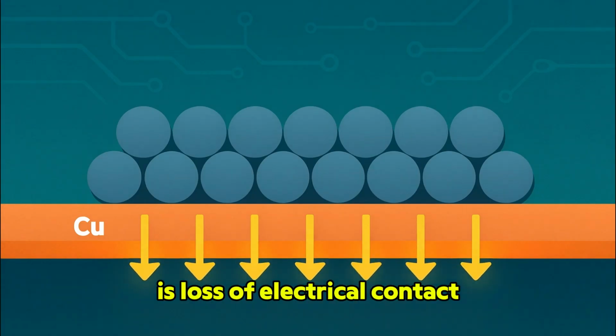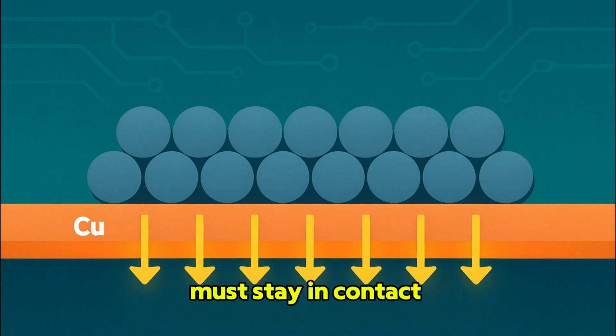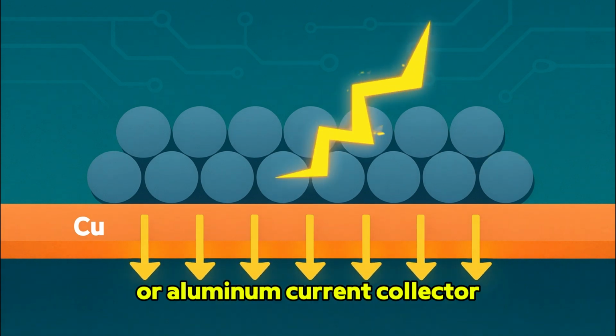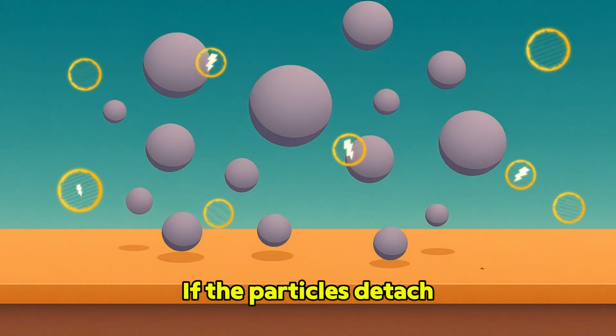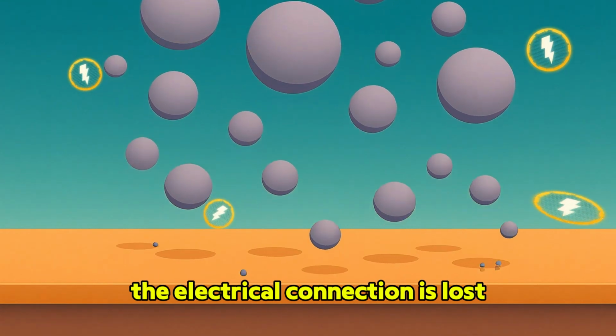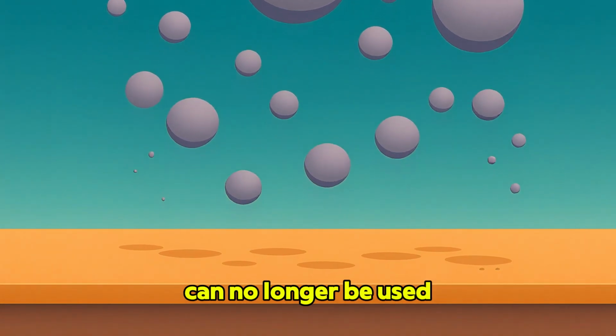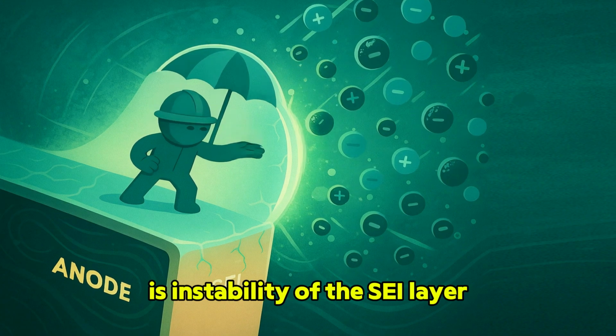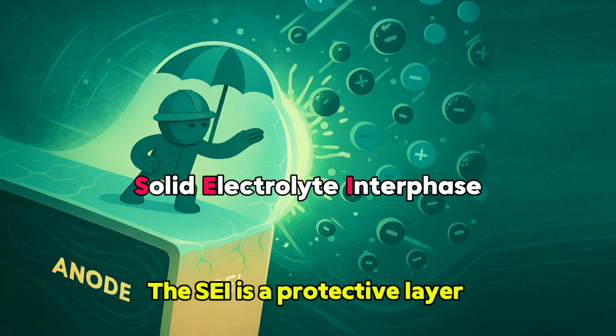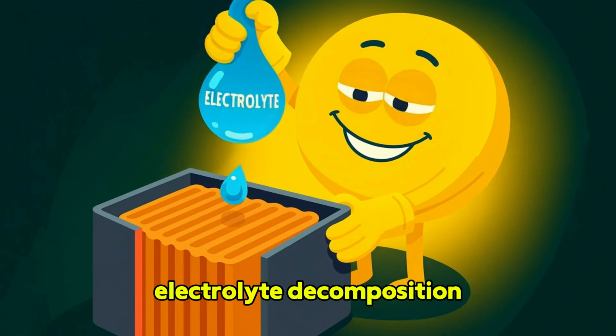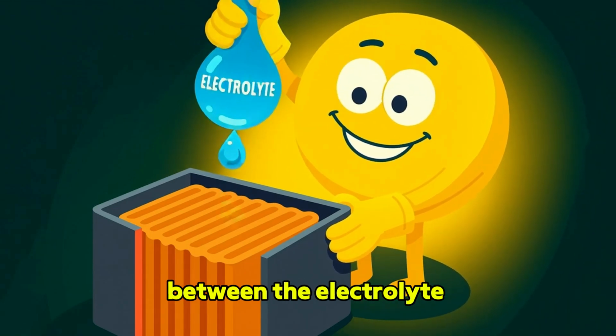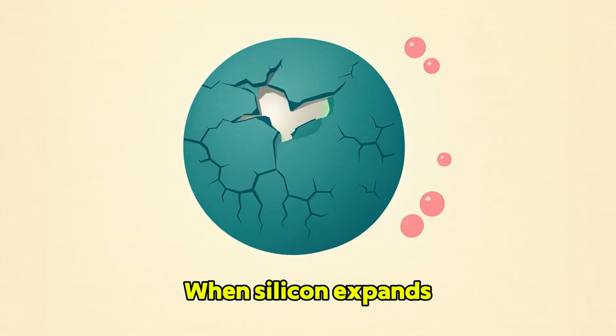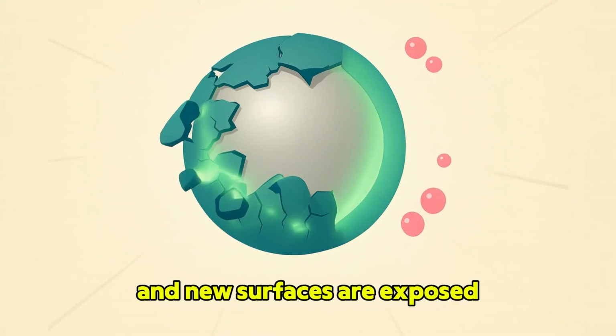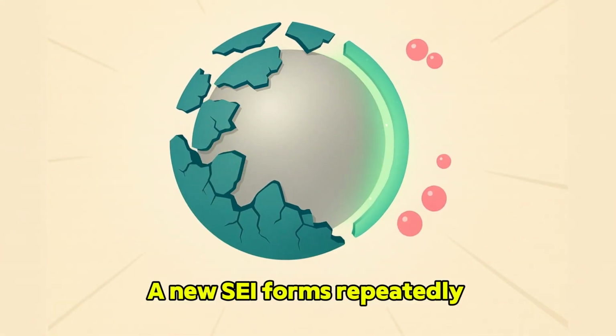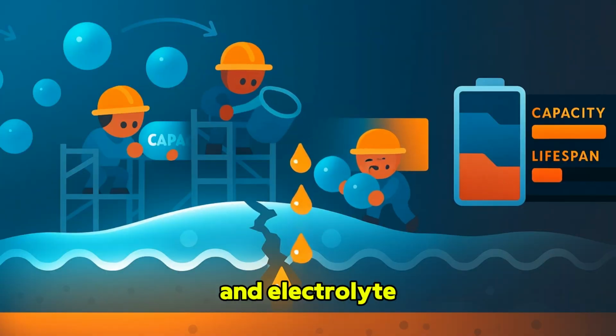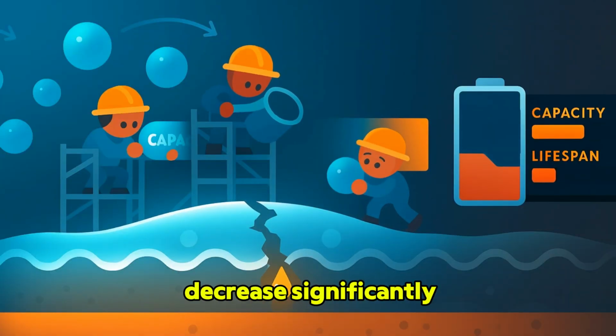The second issue is loss of electrical contact. Silicon particles must stay in contact with the copper or aluminum current collector for current to flow. If the particles detach due to expansion, the electrical connection is lost and the stored energy can no longer be used. The third issue is instability of the SEI layer. The SEI is a protective layer formed from electrolyte decomposition. It prevents direct reactions between the electrolyte and the anode. When silicon expands, the SEI layer cracks and new surfaces are exposed. A new SEI forms repeatedly, consuming lithium and electrolyte until capacity and cycle life decrease significantly.